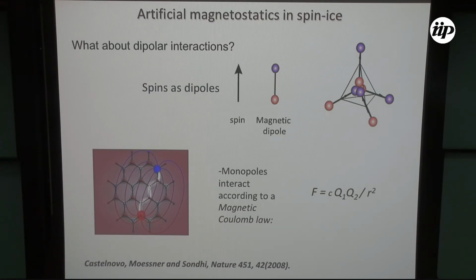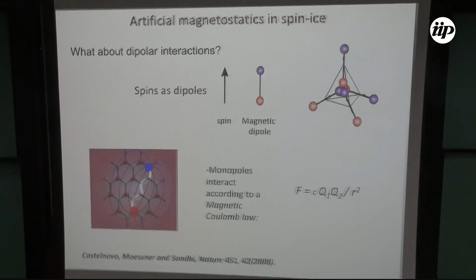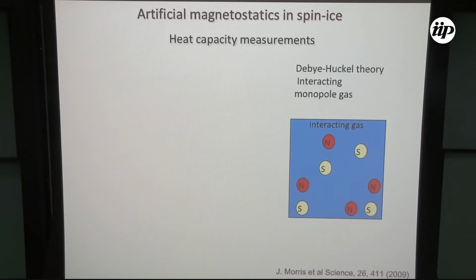Okay, so the other thing that this dipolar interaction adds is that now these excitations are no longer free to move. If you do the calculation, which I'm not showing, but it has been done by Castelnovo, Moessner, and Sondhi in this Nature paper, you see that these charges interact with each other with a simple, if you want, magnetic Coulomb law. So the force between them goes like 1 over r squared. And these charges you can calculate.